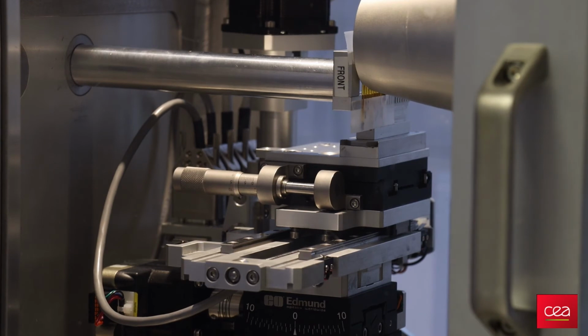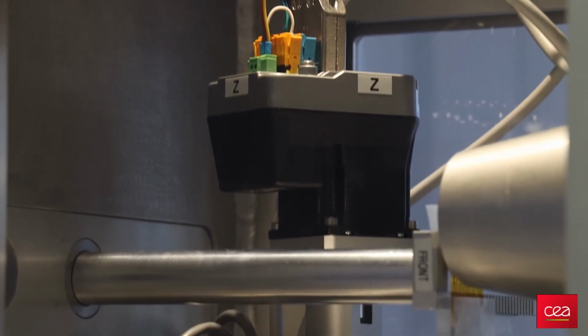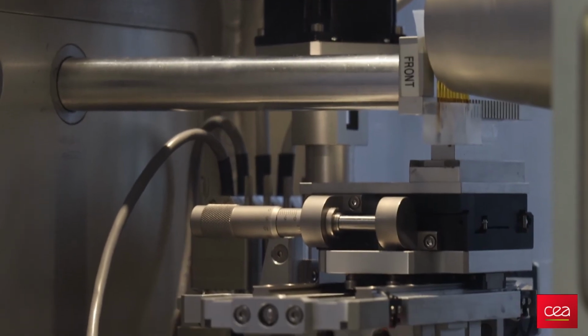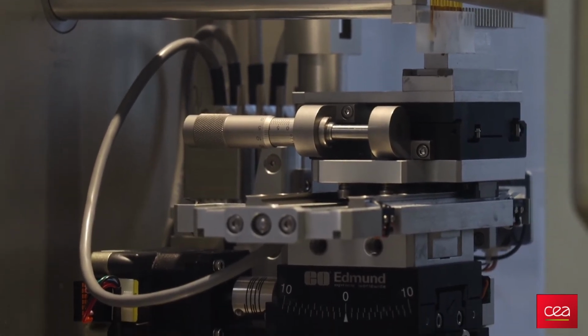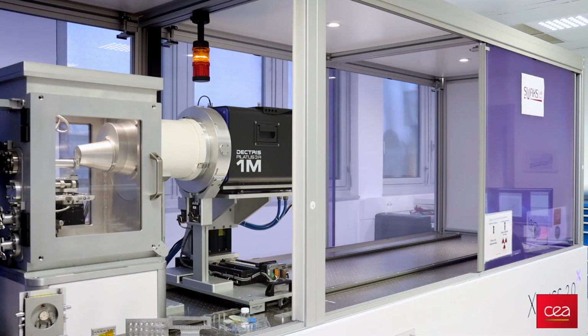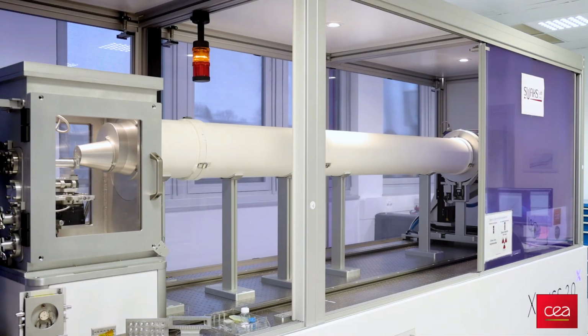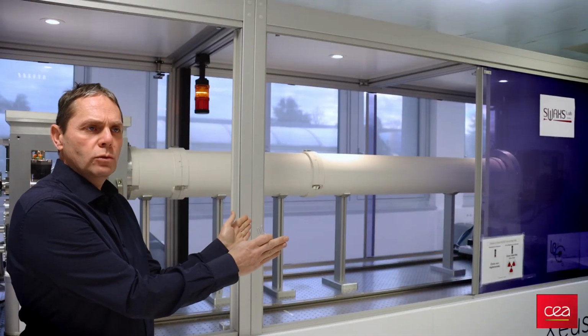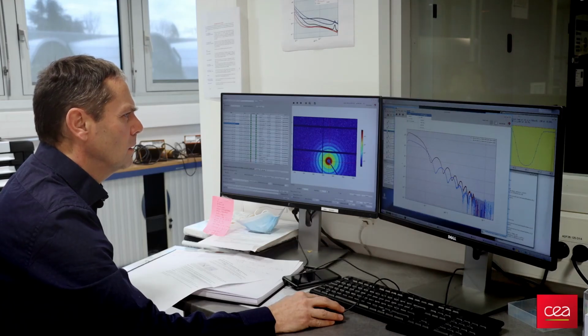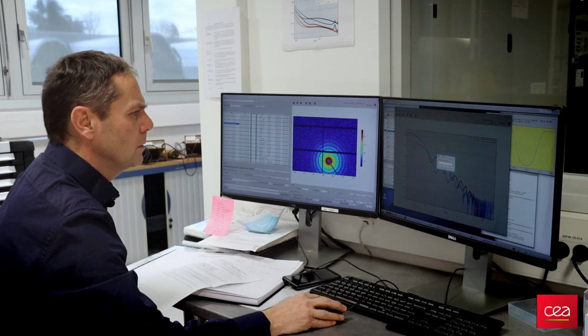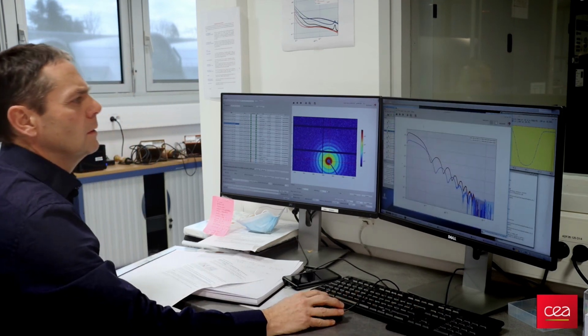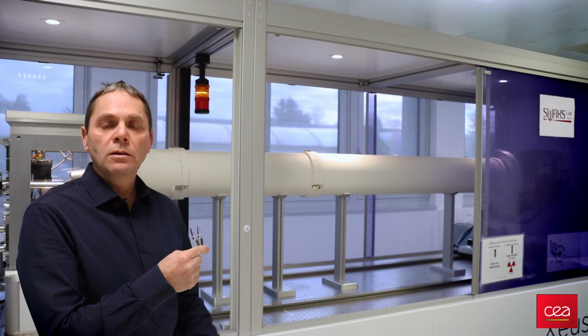This type of laboratory instrument is very suitable for the nanoparticle characterization because you have a very stable source and an accurate detector. On the detector, you can directly integrate the intensity of the X-ray through the sample. Another interest is you can change and measure the distance between the sample and the detector. We can correlate the angle to the meter and to the international system of units. And because the size of the nanoparticle are related to the angle, we can say that the nanoparticle sizes are traceable. Our partners from the PTB in Berlin will demonstrate that in another video.